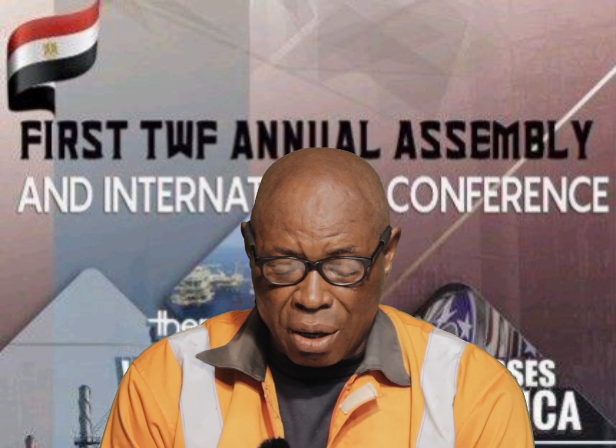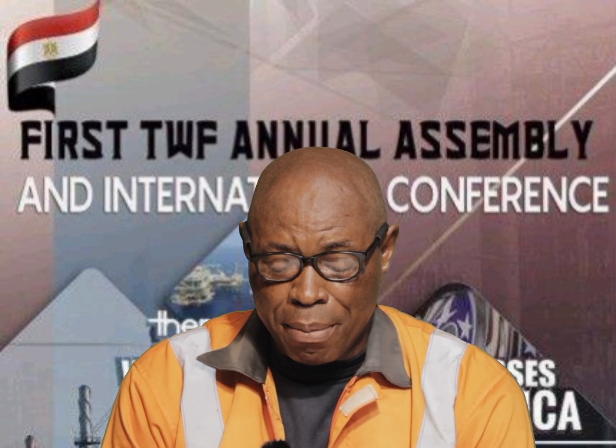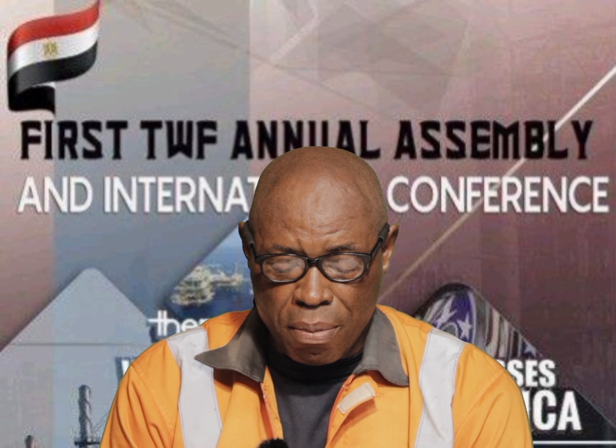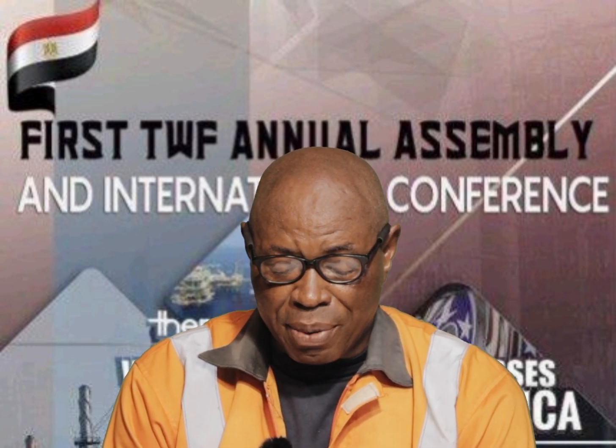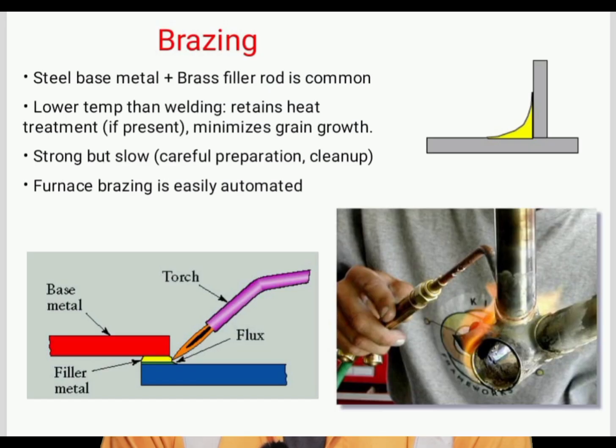Brazing consists of the steel base metal plus brass filler material, which is used at a lower temperature than welding. It retains heat treatment if present, minimizes grain growth, is strong but slow, and needs careful preparation and cleanup. Furnace brazing is easily automated, and it consists of a torch, base material, flux, and the filler material.